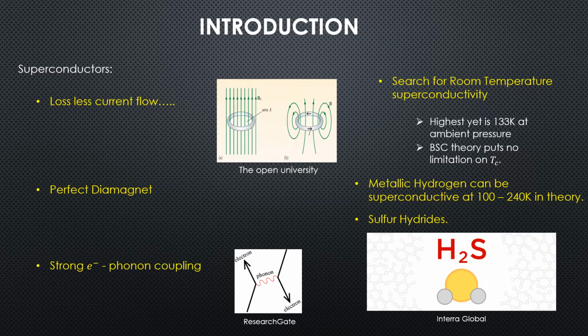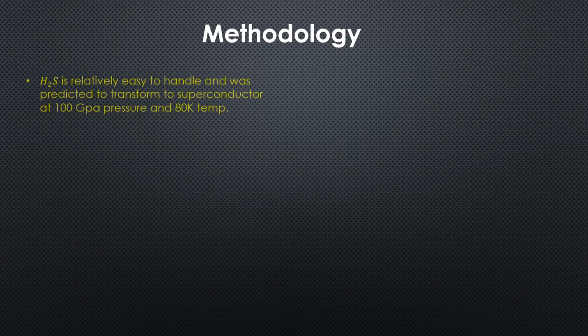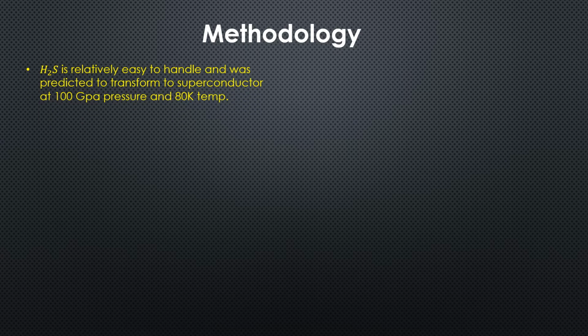So in this study, we are working with sulfur hydrides that show superconductivity at 90 gigapascals of pressure, and are expected to have a Tc somewhere between 100 to 200 Kelvin. For the methodology, we chose H2S because it is relatively easy to handle and is predicted to show superconductivity at 100 gigapascals of pressure and about 80 K in theory.